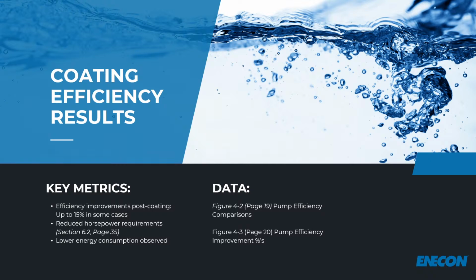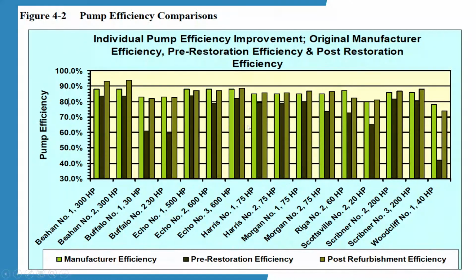So here's the manufacturer efficiency. Here's all the pumps that were done in the study. If you can see that, with the smallest one being 40 horsepower right here, the largest being 300 horsepower. And here's your pump efficiencies right here. You see the manufacturer is right here on this first one. You can see how it really drops down when you're in your pre-restoration. Some of them not so bad, but here on this Buffalo No. 1, the 30 horsepower dropped out a lot. On number 2, it dropped out.